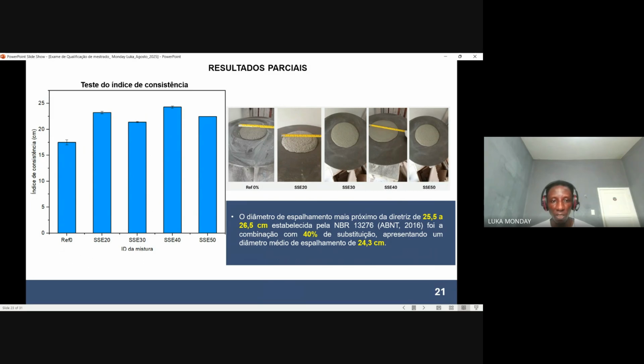On the consistency index test, as the substitution of this material increases, the workability also increases. A workability of 24.3 cm was attained with the 40% seashell EPS substitution level. None of the tests conform to the Brazilian standard, but the 40% substitution rate attains a value closer to the Brazilian standard, which specifies 25.5 cm to 26.5 cm, with 24.3 cm somewhat closer.